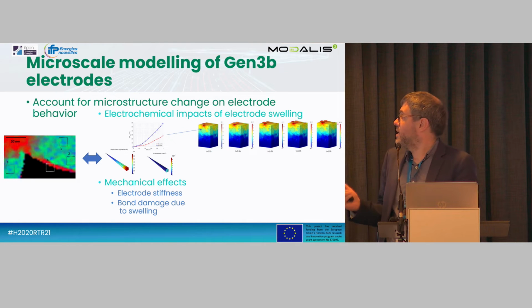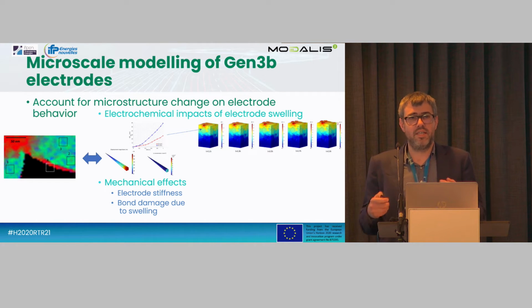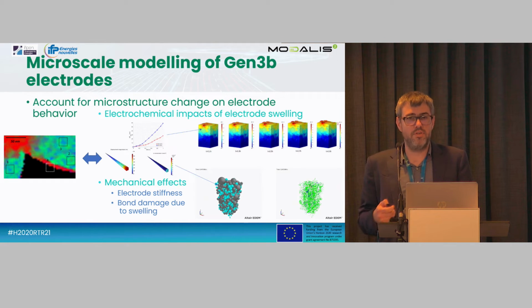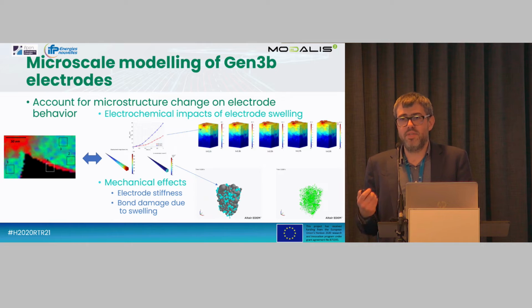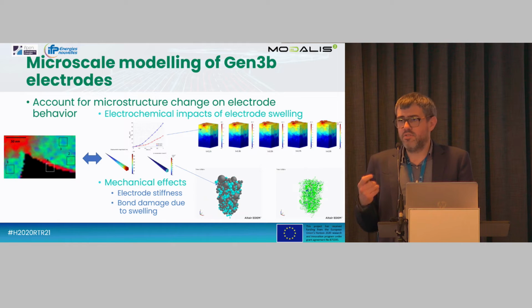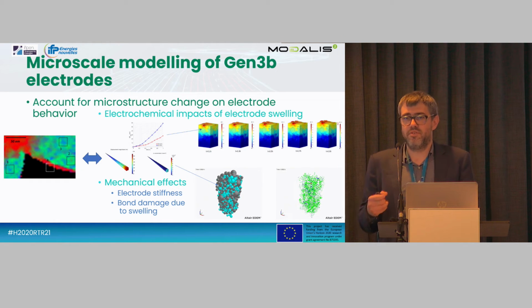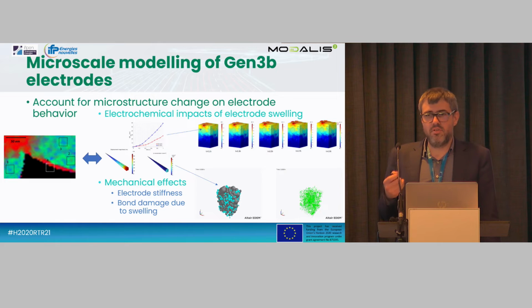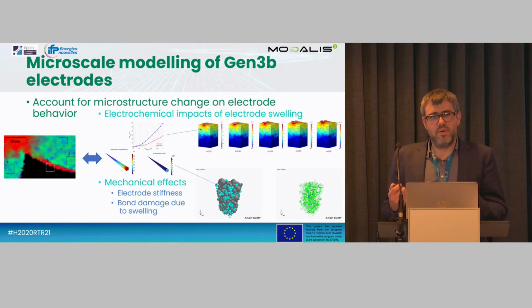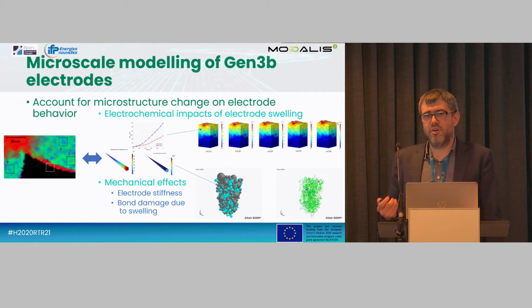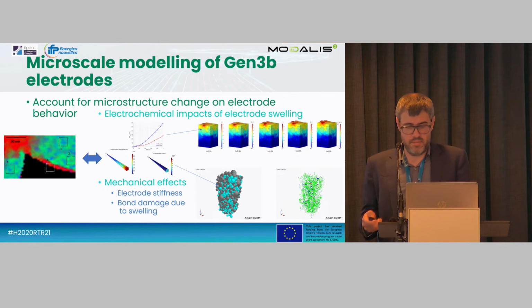So it was done by Solvay in this case in order to understand how the electrode was swelling and some inhomogeneity that we can see in this swelling. And then also in order to focus on the aging and the degradation that we can see in the electrode composite with the binder and so on, DEM simulation has been done in order to understand how the grains are working all together. And also, thanks to DEM, since FEM was not fit for such high deformation, we could also monitor the bonds between the particles in order to understand what was occurring during the swelling and how the bonds were deteriorating in order to evaluate aging of this system.